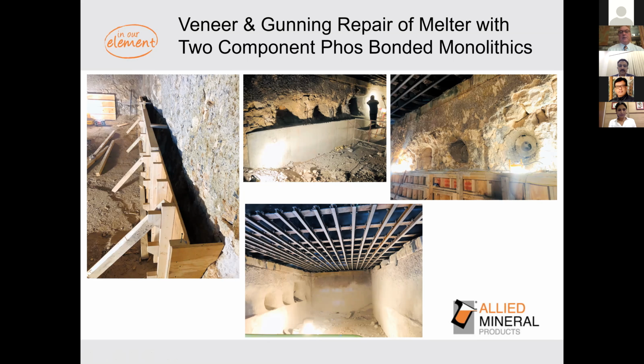It was interesting. We worked with Alcoa. They had been using a colloidal silica gun mix to repair furnaces to keep them going, and we wanted them to use the phosphoric bonded materials, and so they gave us the challenge that you had to get 3 years life in order to justify the price difference between colloidal silica bonded refractory and phosphoric bonded refractories, because they are significantly more expensive than either cement or colloidal silica bonded refractories. And I'm happy to report that we accepted the challenge and we met the challenge. We did receive 3 years life extension by veneer casting.